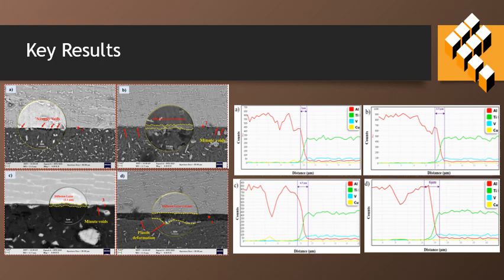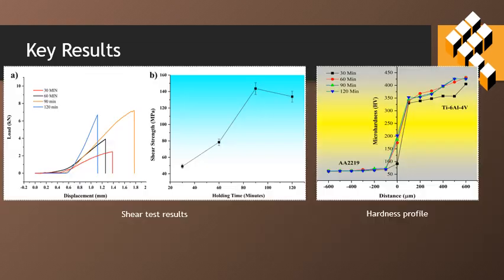The line scan area shows the diffusion depth at the interface of the welded sample. The diffusion depth is also increased with an increase in the holding time. Shear strength is increased with increase in the holding time until 90 minutes, and then after it is gradually decreased when the holding time increased to 120 minutes, elucidating the effect of brittle IMC formed at the interface.